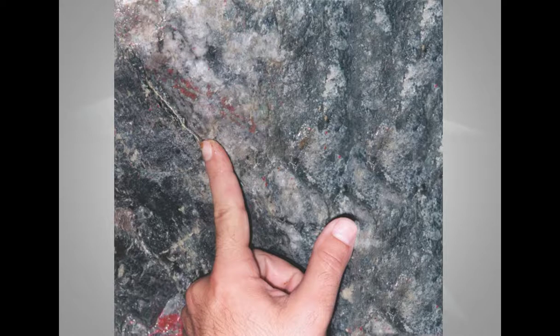Here's an example of one of the intake tunnels at Lake Mead, where the ultrafine was successfully used in a pre-excavation grouting application. The grouting contractors would drill horizontal pilot holes about 80 feet long in advance of the excavation, and they would pressurize the grout, effectively squeezing it into the fissures of the rock in advance of the large tunnel boring equipment. This effectively prevented excess water from entering the tunnel, allowing them to move forward with the project. Not only was this important for keeping excess water out, but with the tremendous head pressures of the water up above, you can imagine how hazardous that could be if there was a significant leak.